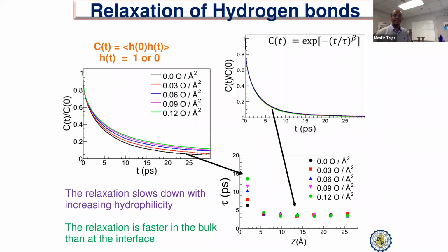We also looked at the relaxation time, how the hydrogen bonds that form and break decay over time. This relaxation time is directly correlated with the lifetime of hydrogen bonding. So the way we do that is at a given time, we have a certain number of water molecules forming hydrogen bonding with the substrate. We follow them, how they form and break, and we generate this correlation. And that correlation decays exponentially, more like a stretched exponential. And from that, we extrapolate the relaxation time tau.